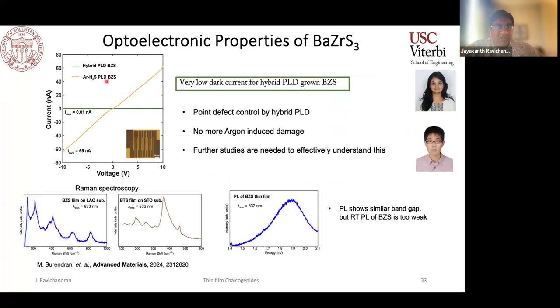So then we took the hybrid PLD barium zirconium sulfide and the argon H2S PLD barium zirconium sulfide films to compare the optoelectronic properties.